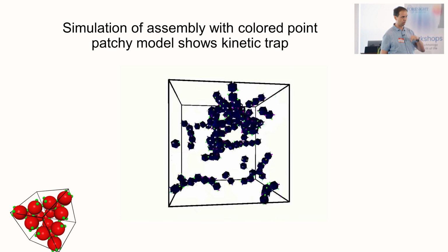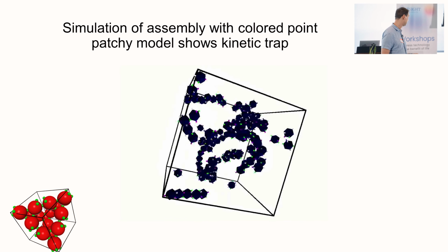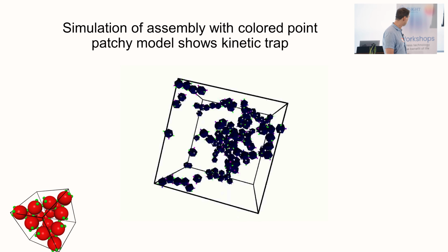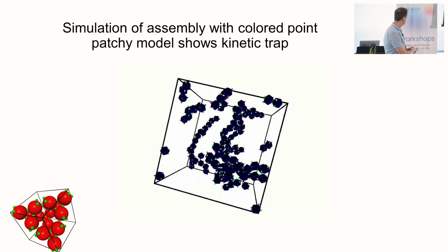But if you, for example, naively think, okay, this guy has 6 neighbors, so let's just say each sticky end binds to every other sticky end, and you start from the disassembled state and wait for the diffusion to do the job for you, instead of getting the crystal, for this particular design, you start forming these long linear filaments. So in physics language, you would call it a kinetically trapped state, or an alternative free energy minimum, which is kinetically preferred. So you never get to the state where you want.